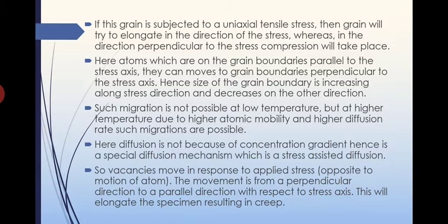Here, diffusion is not because of the concentration gradient. You might have studied diffusion and Fick's law also. There the diffusion is actually happening because of the concentration gradient. Here there is no such concentration gradient. Everywhere the concentration is the same; only if the voids are there, the atoms will be moving to that void space, and it is purely not because of the concentration gradient. Hence it is a special diffusion mechanism, which we can say is stress assisted diffusion.